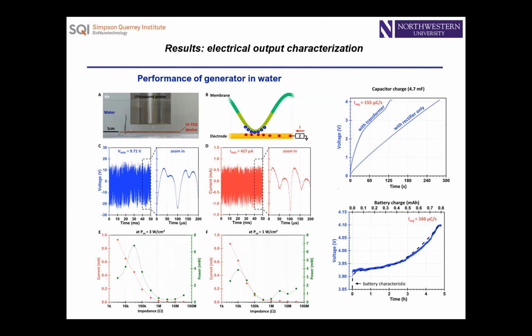We chose that dimension because in 2019, when our paper was published, the size of a pacemaker, for example, was within 3.7 by 3.7, so the device fits the size of the pacemaker. With this device, we also calculated the power level at optimum impedance. It reaches up to 7 milliwatts when 3 watts per centimeter square of ultrasound enters through the device.